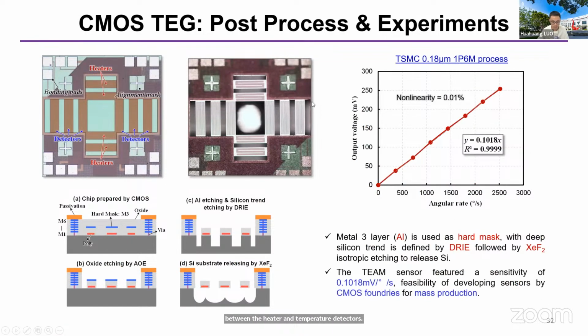And we also did the tape out to fabricate the thermal expansion-based gyroscope by using CMOS MEMS technology. Here, the sensor chip is based on TSMC 0.18 micron 1P6M process. And after receiving the sensor chip, we did the post-processing in our facility at HKUST to etch the oxide with the metal 3 layers used as hard mask, and then to use deep RIE and xenon difluoride etching to release the bottom silicon substrate to form the suspending structure. And the thermal gyroscope fabricated by CMOS MEMS technology shows a sensitivity of around 0.1 millivolt per degree per second. So this shows the feasibility of developing the thermal gyroscope with CMOS foundries for mass production.